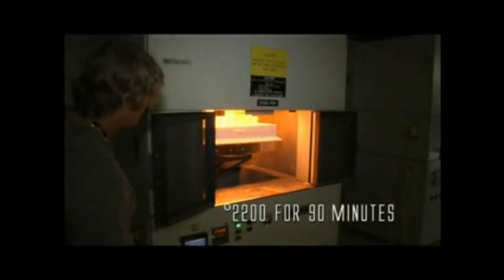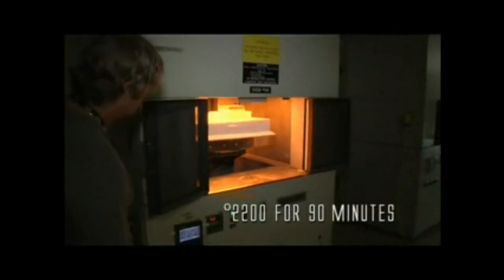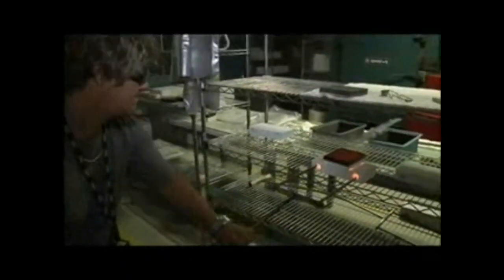The coating has been applied and dried for several hours just at room temperature. Sure. But for the coating to consolidate or sinter, it has to be heated at 2,200 degrees for 90 minutes. Okay. That's what we do in these kilns. And we have a tile in here that's been undergoing that sintering process, and we can go ahead and take it out. The tile's at 2,200 degrees. And you'll be able to see how the black coating starts to cool down very, very rapidly.